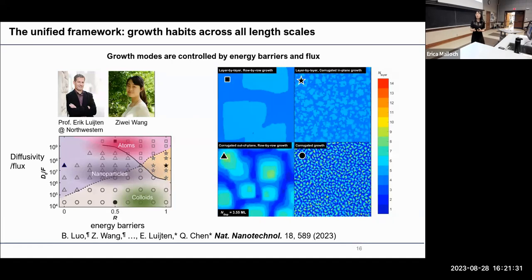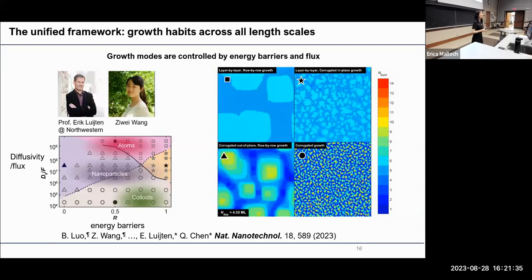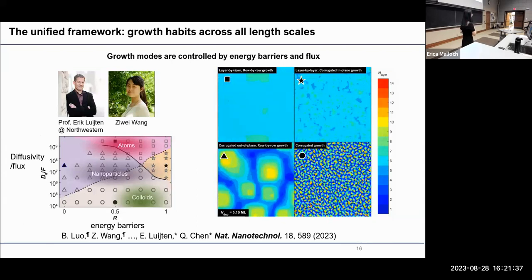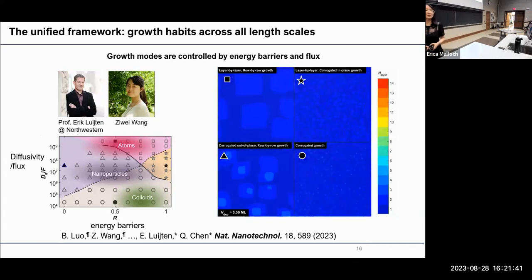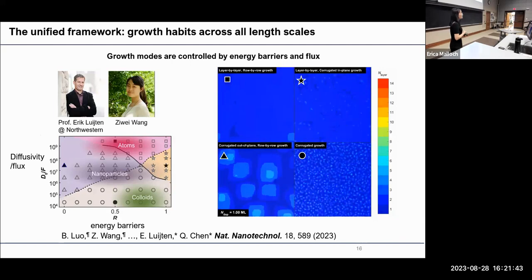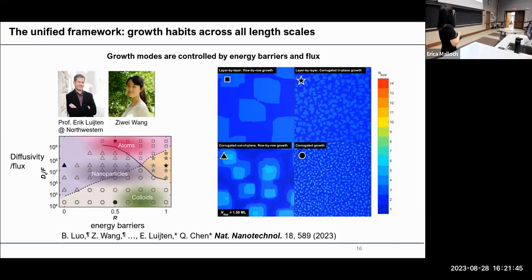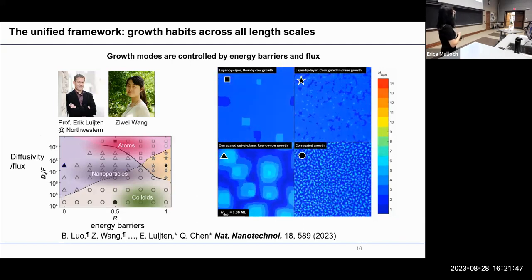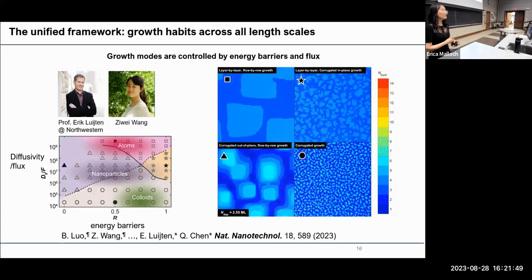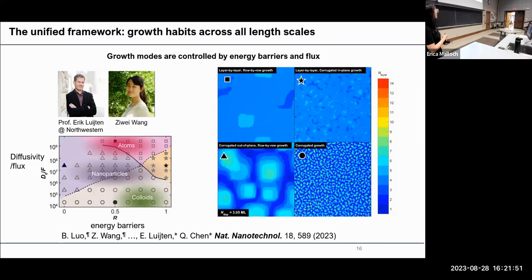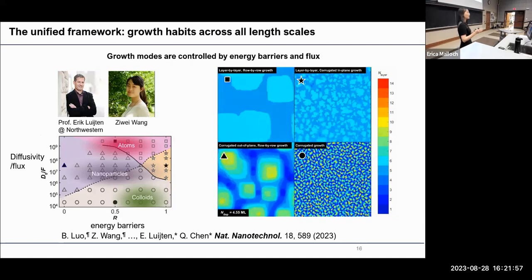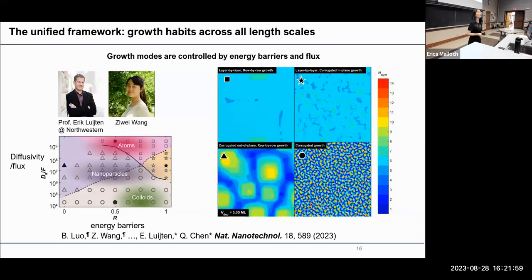In this phase diagram, the x-axis is energy barrier, which is controlled by interparticle interaction. The y-axis is diffusivity over flux, which is determined by mass transport. Interestingly, the different size of particles can actually arise at different locations of the phase diagram. For example, atoms sit at the top, corresponding to layer by layer growth in both 2 growth directions. That's why atoms tend to form into faceted crystals.